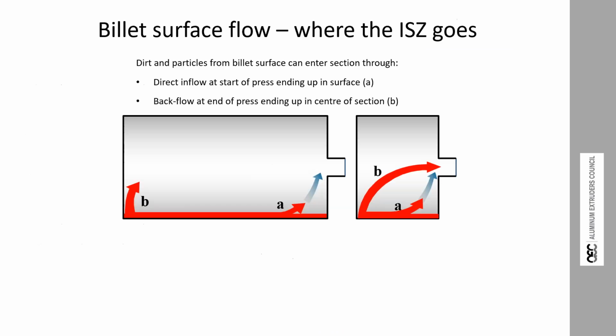Please interject. Here's a little diagram. This is a graphic. There's no intention for the scale to be right, but the red is intended to be the inverse segregation zone. And when we have a long billet, what's happening is the aluminum is flowing from left to right, and then it goes up through the reduction cone to the die. It tends to try and drag some of this material with it. This is called type A or front end inflow. The rest of this layer is plowed up by the dummy block and ends up in the middle at the back.